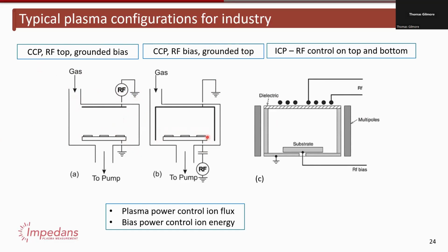If you play with the power on the bottom, you're going to link your ion energy and your ion flux. The higher the power you apply, the more plasma density you get, but also much higher energies. So one solution is to do both. You can apply RF to the top and to the bottom, and use the bottom to control energies and the top to control density. It's fairly straightforward.